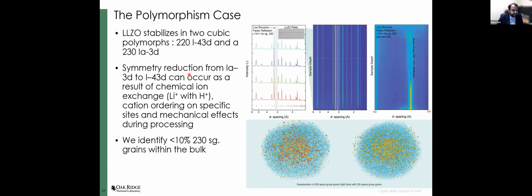And so what we found in our systems, given the way we process them, is that we had a bulk of material in that lower symmetry 220 space group, while a small fraction of it was in that higher symmetry 230 space group. And to do that, we actually devised an experiment using a detector with a high dynamic range, and we were able to track these low structure factor peaks across the thickness of the sample.